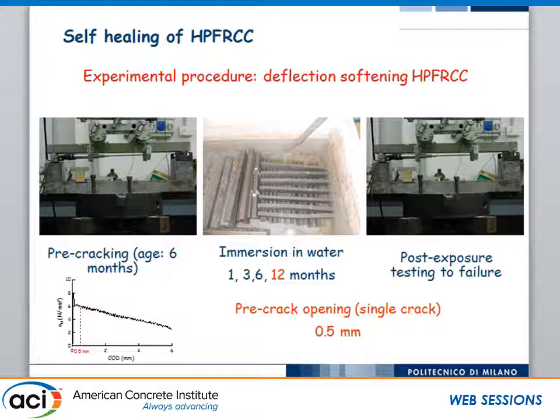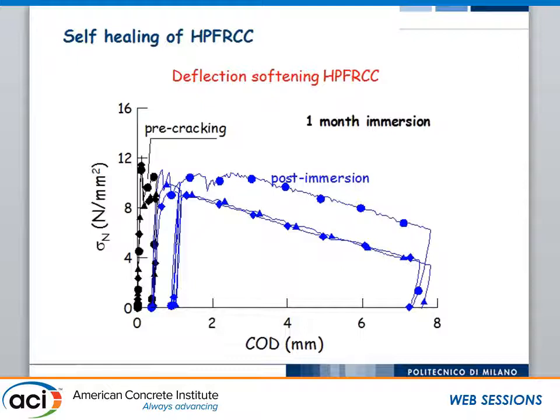We put the specimens in water, and the 6 month tests were done just last week, so we have specimens still waiting in water up to 1 year and more. We retested the specimens up to failure, and we got a result like this. You see, the black curves are the pre-cracking curves. You cannot see the pointer. Okay. And the blue curves are the curves that we were able to measure after the conditioning in water and